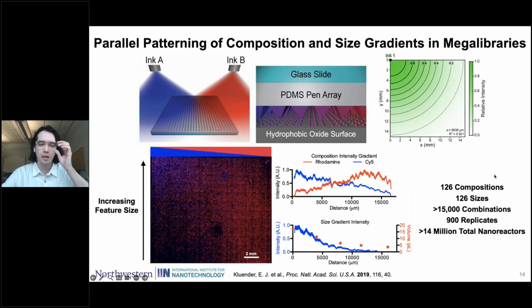So now beyond this serial generation of composition gradients, we're also exploring a lot of parallel techniques to make composition gradients. And so what we're doing in this case is creating the composition control on the pens before patterning. So we can take 2 different precursors, in this case A and B, and spray them onto the pens. And so now we have from left to right a gradient of composition, and then also from top to bottom a gradient of the volume of ink that we're putting on the tips. And so now we can pattern on the surface.